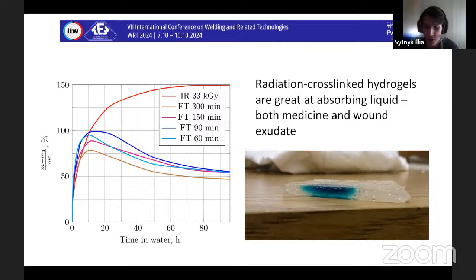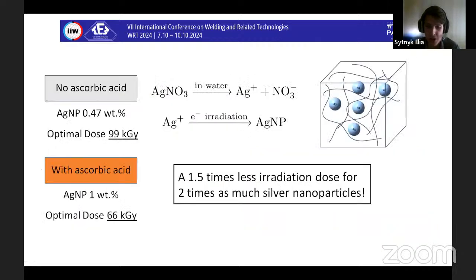Great permeability of liquid and oxygen are necessary conditions for successful wound healing, but the gels themselves do not have antibacterial properties, which can cause harmful bacteria to grow inside the hydrogel bandage and cause a wound bed to get infected. Silver nanoparticles can be used to enhance the antimicrobial properties of gel polymer materials while using various methods of cross-linking gels: irradiation, cyclic freezing and thawing, or plasma. Although electron irradiation can be used for silver ion reduction as well as cross-linking, it can be rather challenging when increasing the silver nitrate concentration above 0.01% of mass. In the case of an effective silver concentration, it will take a considerably higher dose of irradiation for gel to form crosslinks and obtain their mechanical properties, increasing the cost of hydrogel bandages.